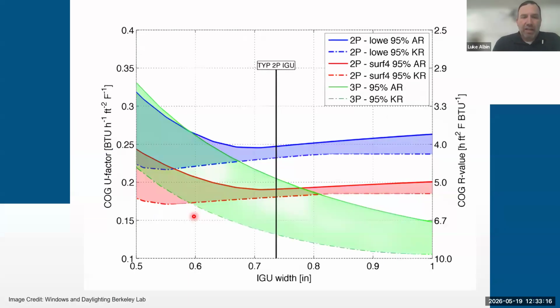As we take a look here, just again a snapshot. What we have on the left side is the U factor, converted on the right side as the R value. So really the more efficient are going to be down in the right bottom quadrant. The IGU width is on the horizontal axis here, and you'll see that this black line represents typical dual pane IGU width. It's about 3/4 of an inch, 11/16 is typically what most domestic manufacturers will run.